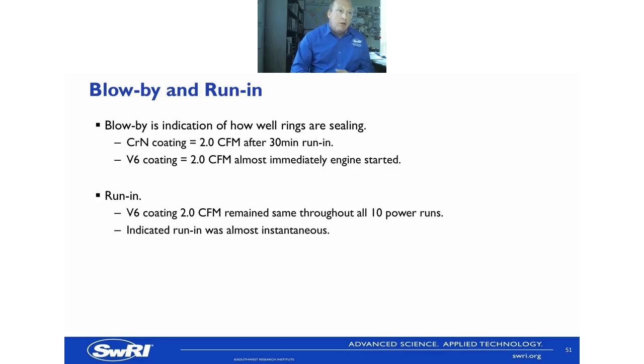Interesting was the blow-by and run-in. So blow-by is an indication of how well those rings are sealing, like I explained at the beginning. You want to reduce blow-by. The CRN coating was down at 2 CFM after 30 minutes of running, whereas the V6 coating effectively ran in almost immediately and was down at 2 CFM, basically as soon as the engine started and they were taking the measurements. From a running perspective, the V6 coating remains the same at 2 CFM through all 10 power runs. And this indicated that the running was almost instantaneous because that blow-by did not change throughout the testing.